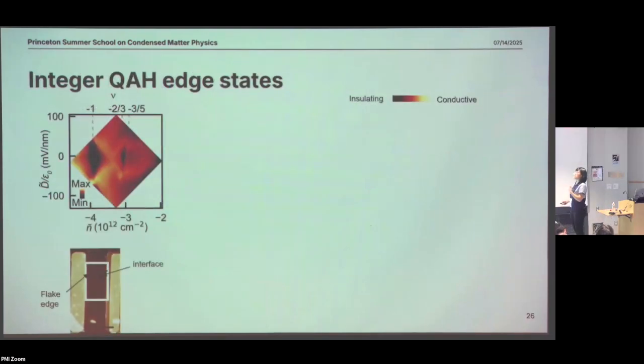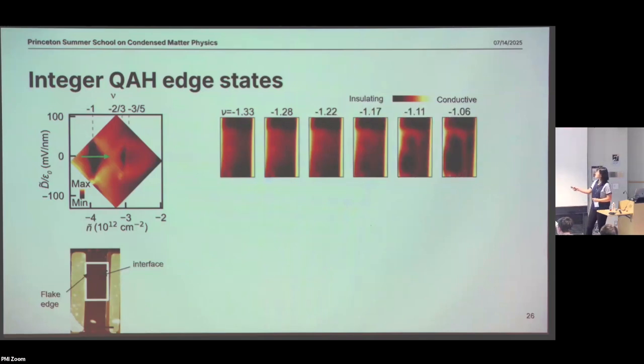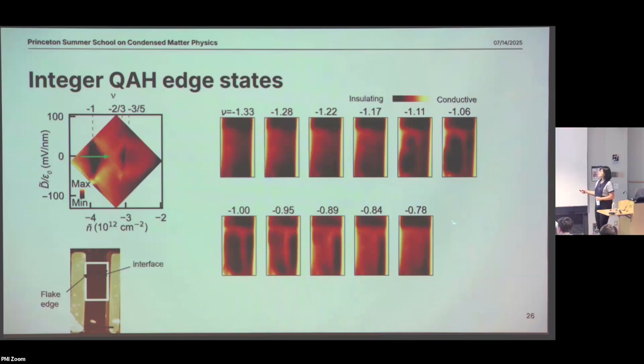Okay, so we first went to the integer quantum anomalous Hall states by changing the top gate voltage and the bottom gate voltage, following this green arrow. By following that, we map out the signal from nu equals -1.3 to -0.78. At nu equals -1.3, or the other extreme, it's pretty homogeneous and conductive everywhere. But in the middle, close to nu equals -1, there's a sharp contrast between the edge, which is bright, meaning conductive, and the bulk, which is pretty dark, meaning insulating. That is the signature of the quantum anomalous Hall edge states at nu equals -1.